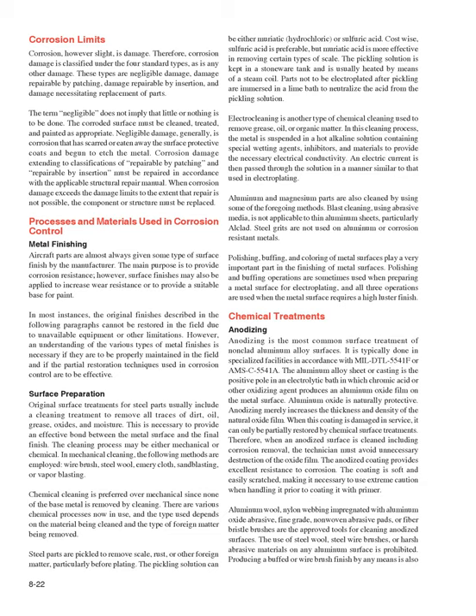There are various chemical processes now in use, and the type used depends on the material being cleaned and the type of foreign matter being removed. Steel parts are pickled to remove scale, rust, or other foreign matter, particularly before plating. The pickling solution can be either muriatic, hydrochloric, or sulfuric acid. Cost-wise, sulfuric acid is preferable, but muriatic acid is more effective in removing certain types of scale. The pickling solution is kept in a stoneware tank and is usually heated by means of a steam coil.